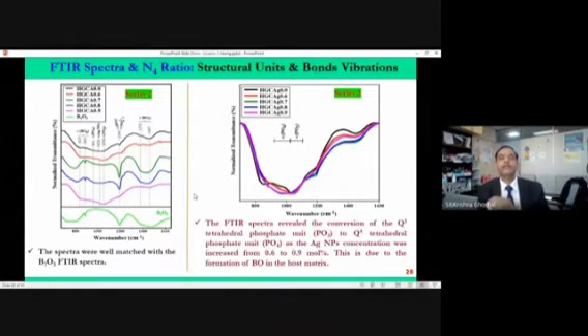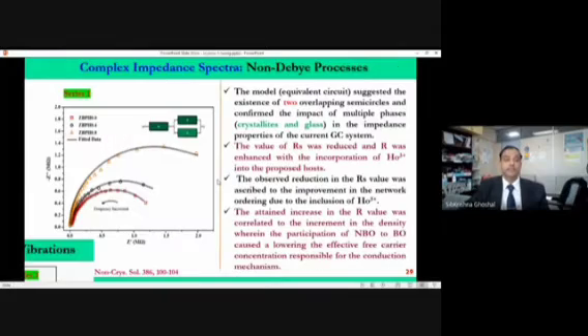Go for FTIR analysis, look at the spectral weight, and from those weights we can clearly find the concentration of those units, and then we confirm that they are there in the system. Then we could do the impedance spectroscopy to look at the source of polaron or bipolaron physics. Then we look at the impedance, resistance, and also the